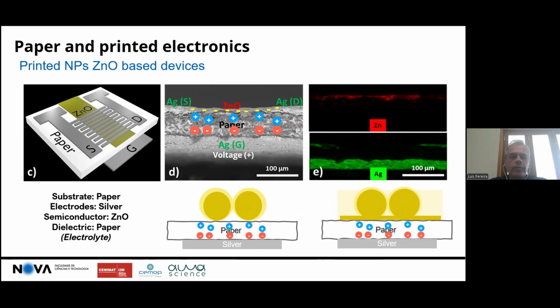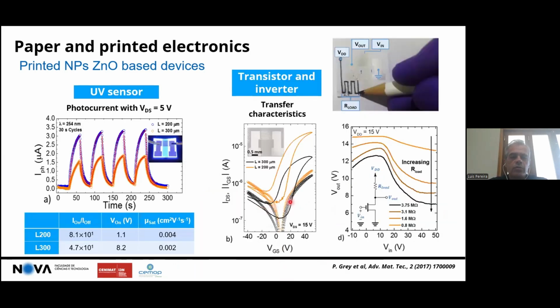And so you can have devices like a transistor working with, I would say, very bad performance, but you can already demonstrate that you can modulate the current, even requiring high voltage, and you see a high hysteresis. We have also demonstrated UV sensors if you don't operate the gate, and if you connect some resistors, you can demonstrate some inverters. But the most important point is that we have demonstrated that you can modulate it without requiring high annealing temperatures or long processing time.